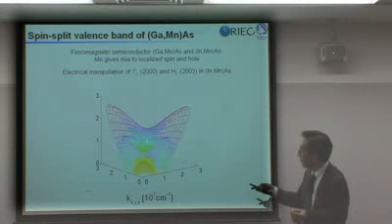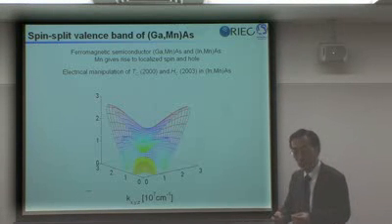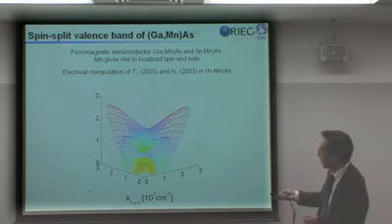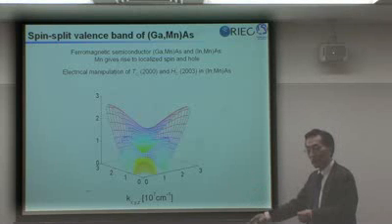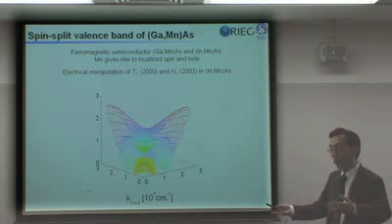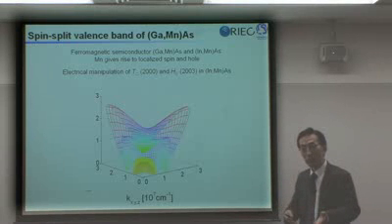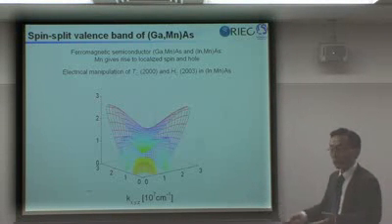So these states have different spin orbit interaction. So if you can change the carrier concentration, we might be able to emphasize this spin orbit interaction over that spin orbit interaction. And spin orbit interaction is the thing that determines magnetic anisotropy, or the direction of magnets.